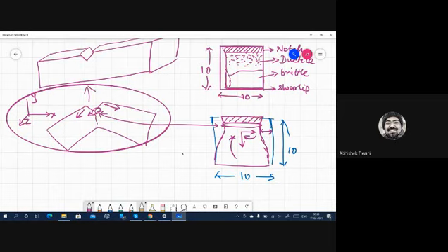But so far, lateral strain is the strain here, right? So initially, from the center, this dimension was 10, right? And then after testing, you have this dimension, which is 8 mm. So the total displacement on the half side is 2 millimeters. So delta U is 2 millimeters divided by, oh, it was not 10, it was 5.